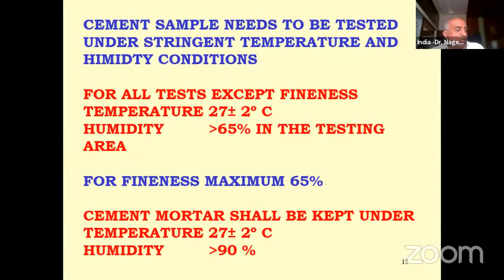So cement mortar cubes are cast and they shall be kept in a humidity room or humidity chamber, which has a humidity of more than 90%. These are the requirements that really need to be looked into in a testing laboratory, without which the results will vary. You will not get reliable results. The results can change.